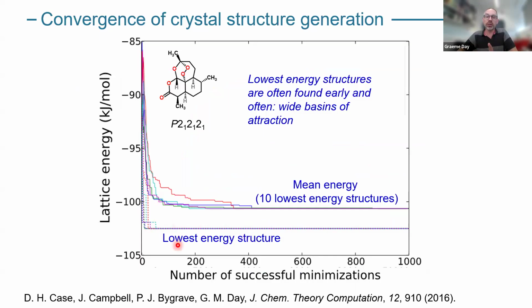You see this actually converges much earlier, after, in this case, only a few tens of trial structures. And this is because those lowest energy basins tend to have wider basins of attraction. And so we hit those basins early on in the search, whereas some of those higher energy ones are much narrower, and those are the ones that are harder to find.